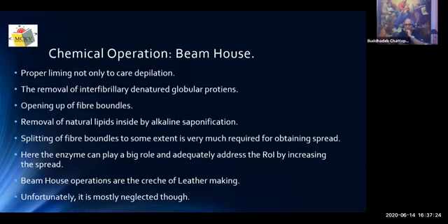Opening up of the fiber bundles, removal of natural lipids inside by alkaline saponification, and the amount of swelling of the fiber bundles are important. Here again, for splitting the fiber bundles and removal of natural lipids, enzymes can play a big role, if done properly, and adequately address the return on investment by an increase in spread.